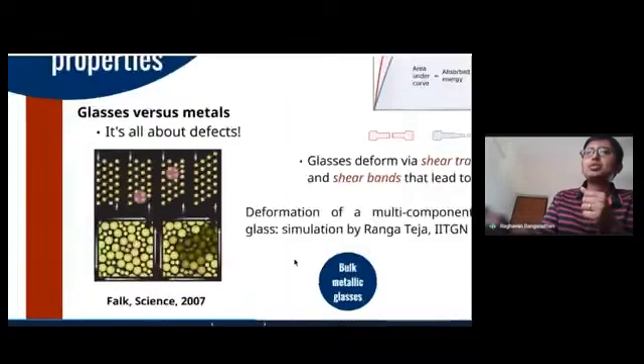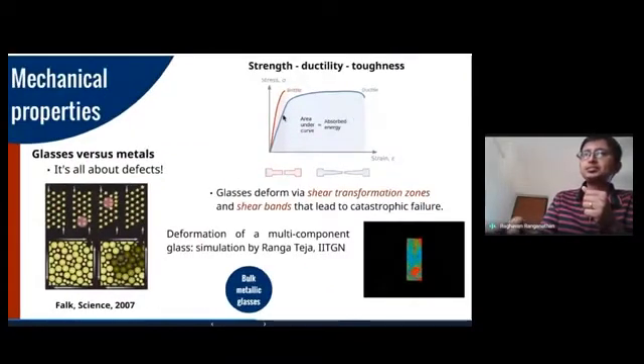So what we see is a small region here that's highlighted in red. These small localized regions in glass will undergo some sort of deformation at a very local scale. Okay? And these will basically expand and communicate with its neighbors. And this will basically lead to a catastrophic failure. So if you have a pre-existing defect in a glass, this defect can essentially grow, and that's what leads to the brittle nature of glass.